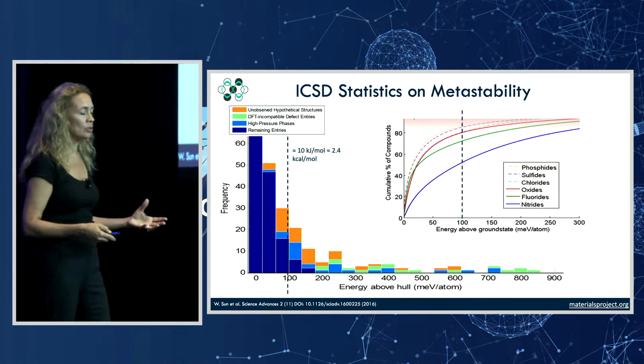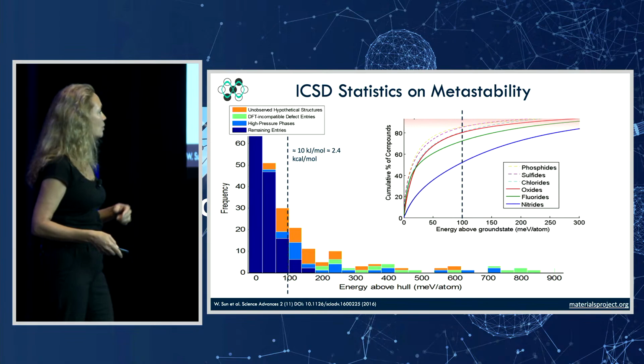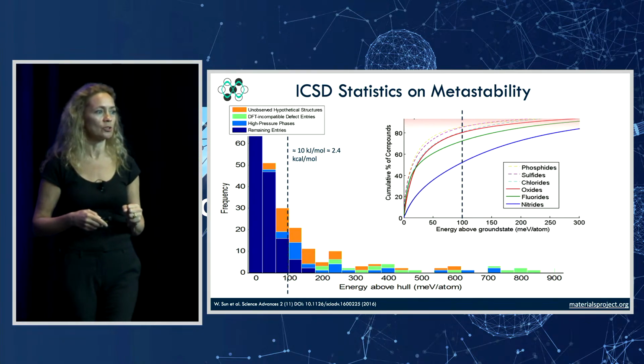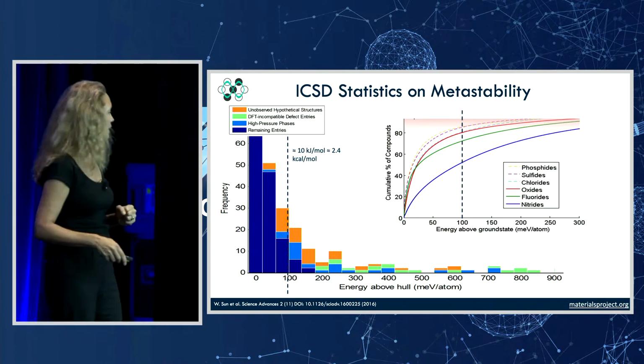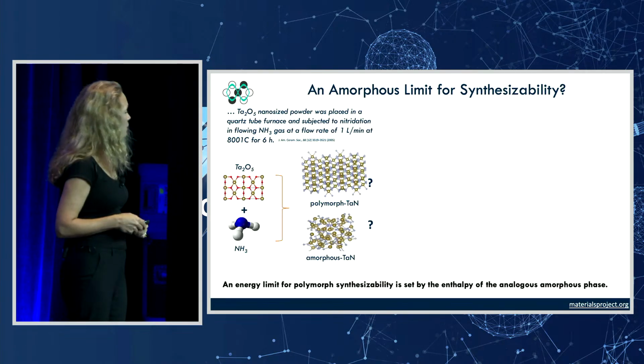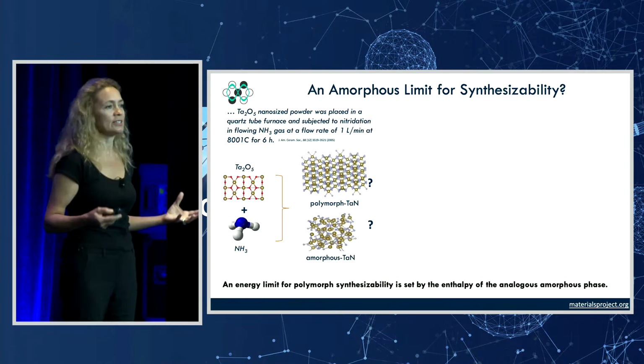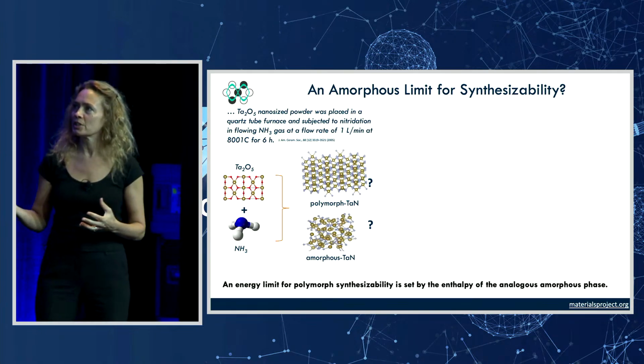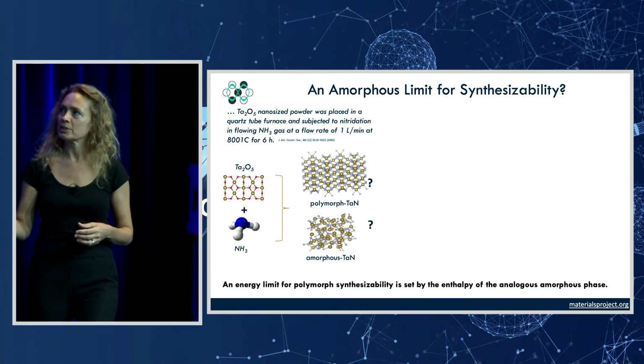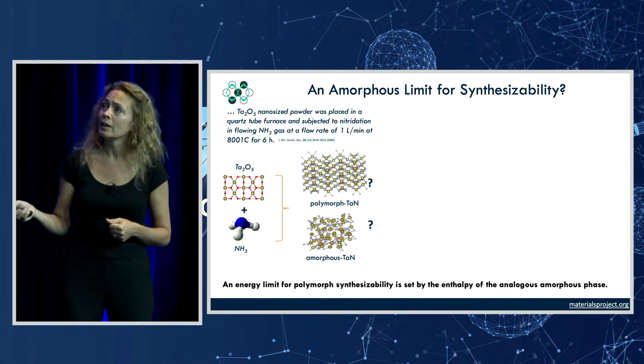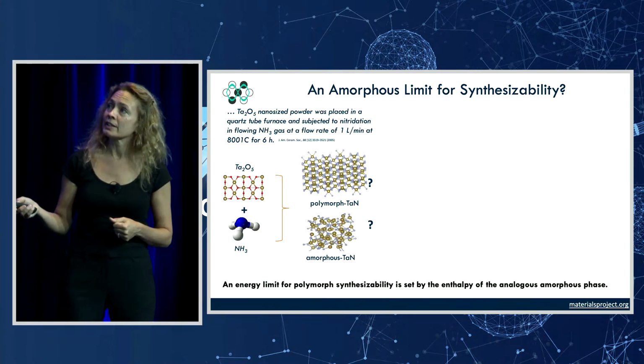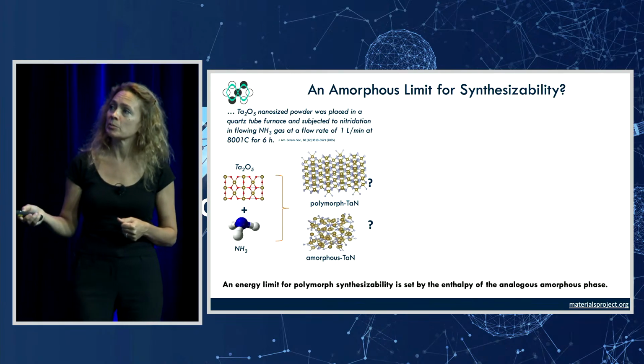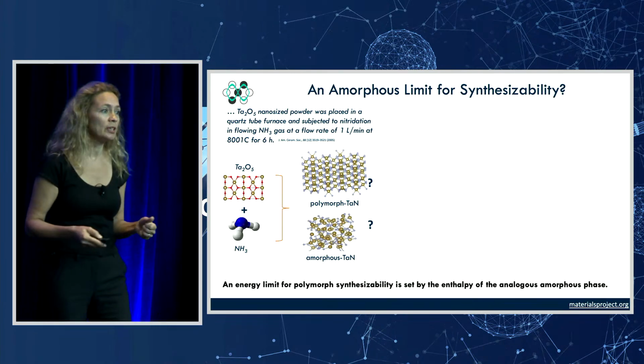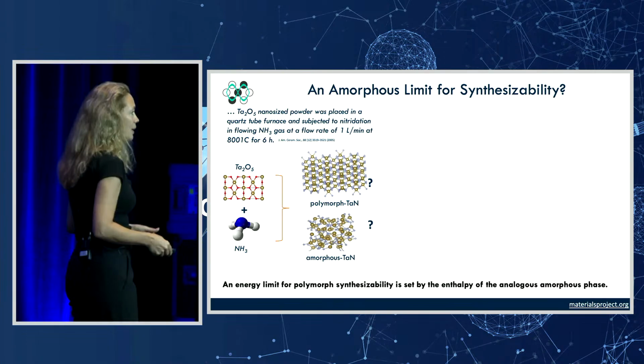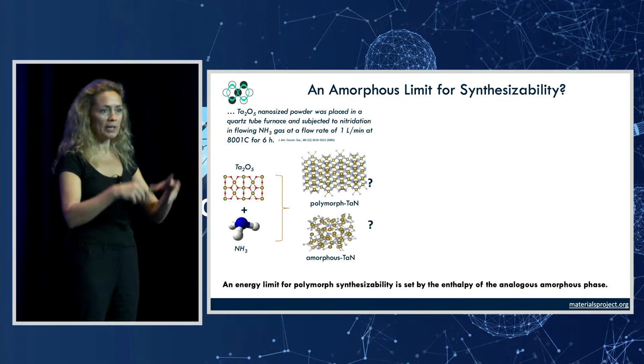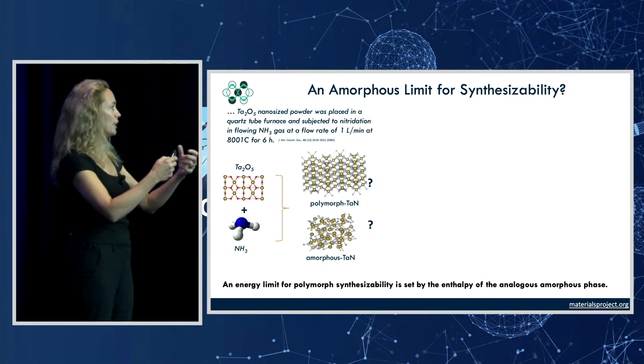So there are probably better metrics out there for when something is synthesizable, when we can send our experimental counterparts into the lab and hope that they can make something. So we started thinking about the process of synthesis. If you want to make a particular polymorph, a particular crystal structure, let's say in the tantalum nitride space, you may be mixing, and this is from a paper, tantalum oxide and ammonia, and you heat that up. The first thing that's going to happen, well, you're going to break bonds, right? You're going to break up your precursors, and you're going to make something.